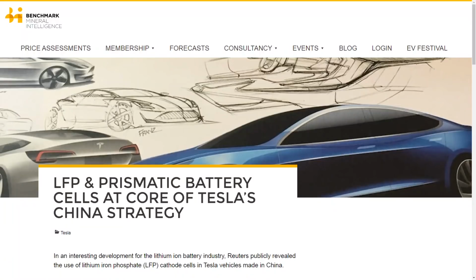There are some safety issues, but the energy density is improved with high nickel cathodes. The LFP, as you've seen now, this whole thing with the blade, and Tesla are going to use LFP in their short range Model 3 in China. What they did is they managed to, if you look at the energy density at the cell level and then